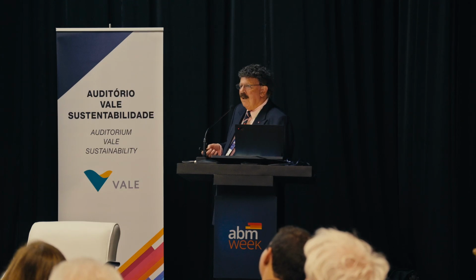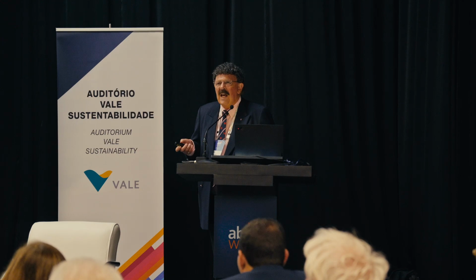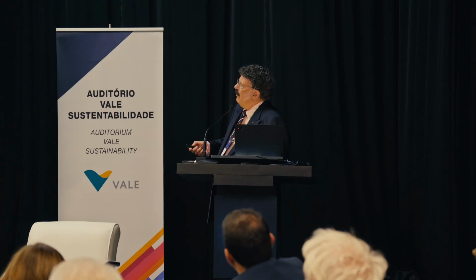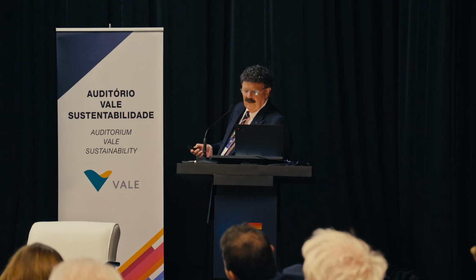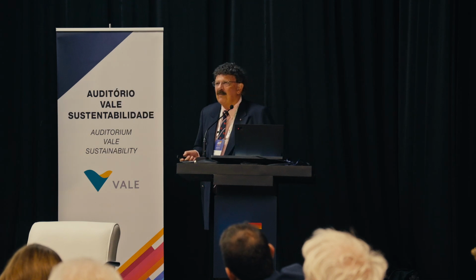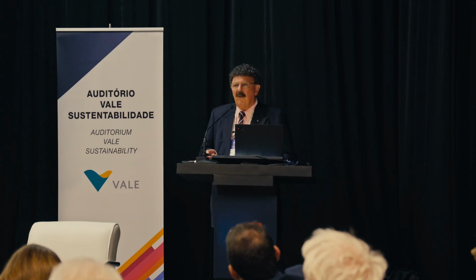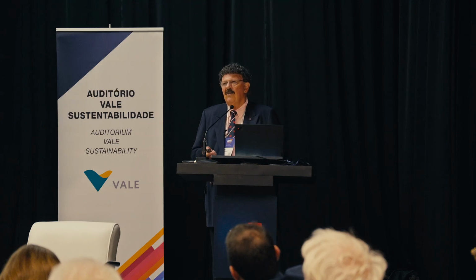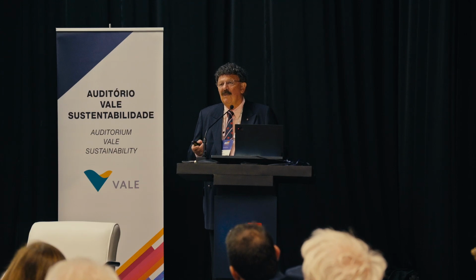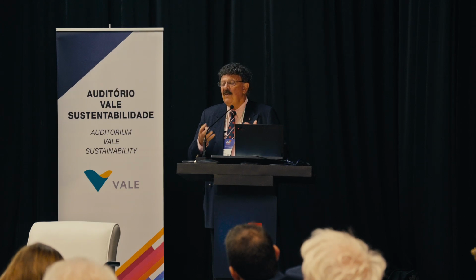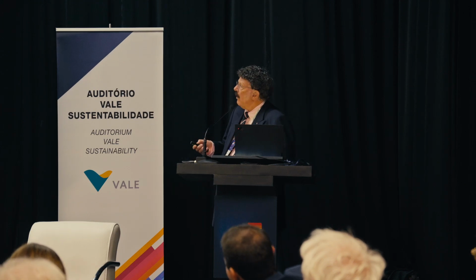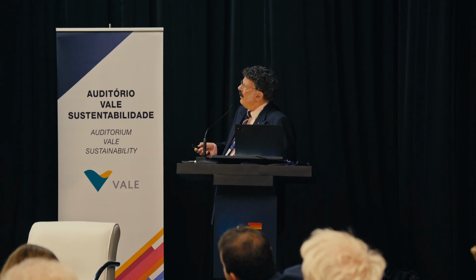The toughness of the alloys I showed you before was all less than 10. This one is very, very high. The toughness, they stay above about 50 in all conditions. They're about 200 or so at room temperature, but they have toughnesses of close to 100 megapascals root meter at liquid nitrogen temperatures. This is a BCC material. It should have a ductile brittle transition. The toughness should have dropped to 0, but this is very, very high. And so it's a very interesting material.